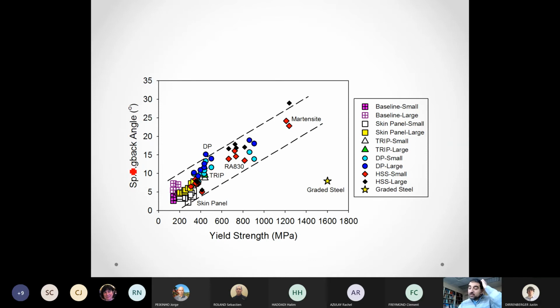If we look at a lot of steels that have high strength, we can bend them, and when we remove the force, the steel springs back because of the large elastic deformation. In the graded material, because the outer layer is soft, we don't have as much spring back, and we see a clear benefit where it really outperforms the general trend we find in steels.